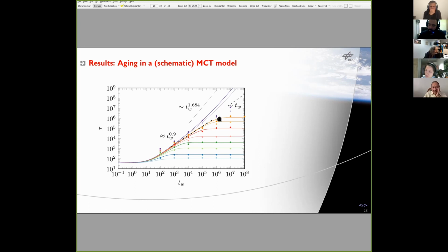If you look carefully or not too carefully in this intermediate regime between the 2 plateaus, you could try to describe this with an effective power law that would then have an exponent slightly less than 1, because the exponent 1 is the truly asymptotic solution that emerges, and you observe for all these others a crossover. And that is my current understanding of the sub-aging that has also been reported for various aging experiments in glasses. That is basically a crossover, because you cross over from something constant to something other constant on a log-log scale, and that looks like a power law.